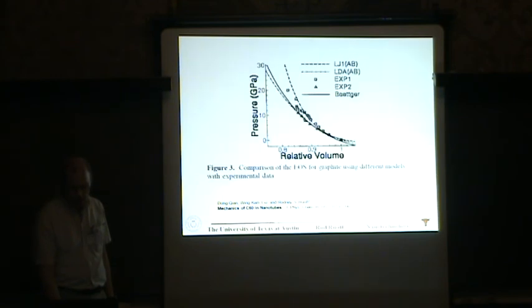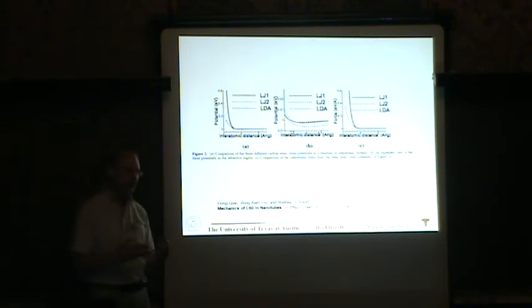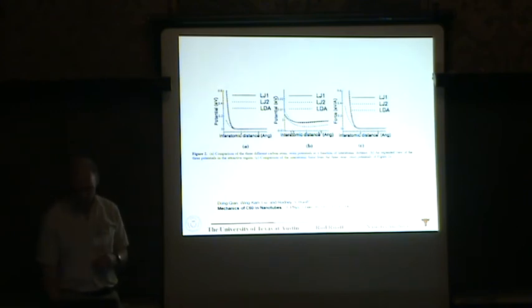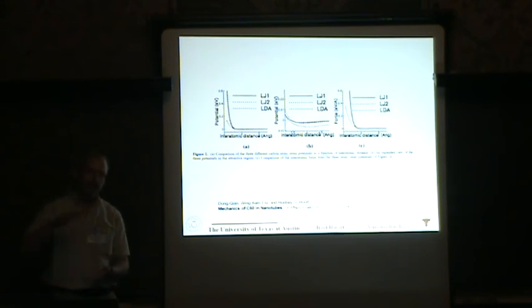And I'll jump over. Well, we used a couple of different potentials, and I'll skip that. It's pretty straightforward. We used Lennard-Jones at large distances, and we used LDA at short distances. It's well known that the inverse 12 dependence is much too stiff, it's too rigid compared to more appropriate potentials at short interatomic distances. So we essentially splined those together. And the LDA comes from David Tomanek, and it was compared to full ab initio calculations by Boettger that mapped out the equation of state of graphite as a function of pressure.